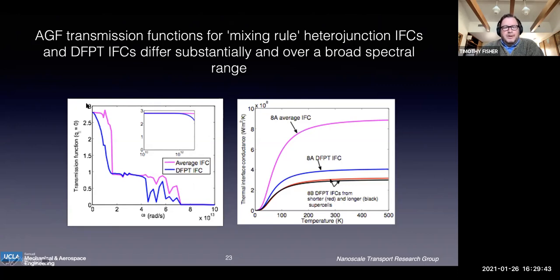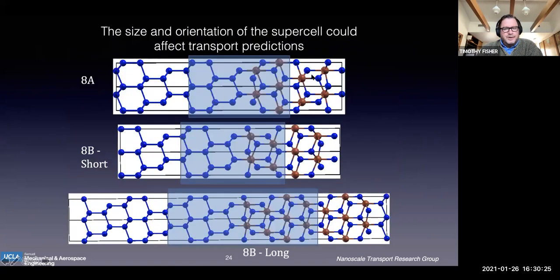And in the magenta or fuchsia colored, that's what a lot of people had done up to that point, which is to take the bulk bonds of silicon and the bulk bonds of cobalt silicide and average them and say that that's what the nature of the heterogeneous bond is, right? And it's a really intuitive, good first guess. But it turns out that when you do that, the interface conductance predictions are off by a factor of two or so, which frankly, if you're going to plot everything on a log scale, that's not so bad, but we wanted to not plot things on a log scale. So that's where we started.